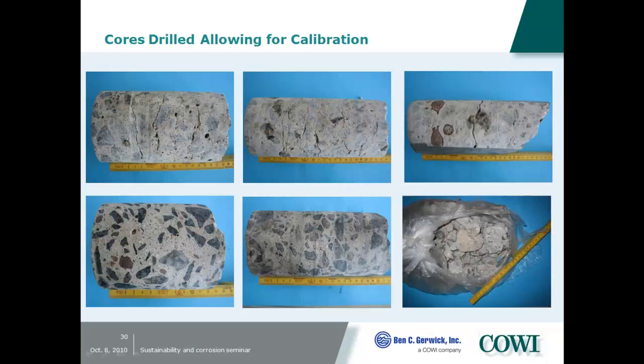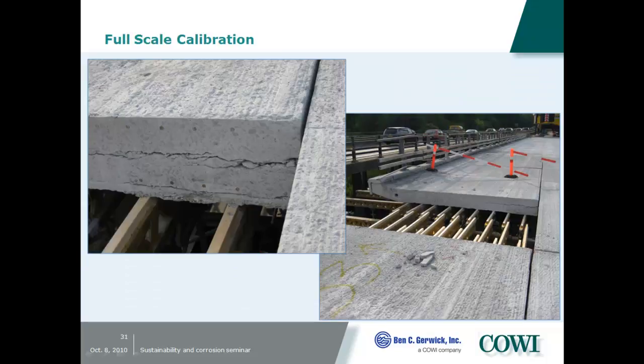Based on these findings, we concluded that this bridge was not in a good shape. So from making an upgrade in load carrying capacity, we recommended that they take this bridge down. This is a full-scale calibration. You can see they've taken away the membrane on the bridge, and they've cut it to take it away in sections. It was the right decision that we took, making the non-destructive testings, which then of course turned out to be very destructive as we took down the bridge afterwards. And what caused this is alkali-silica reactions.